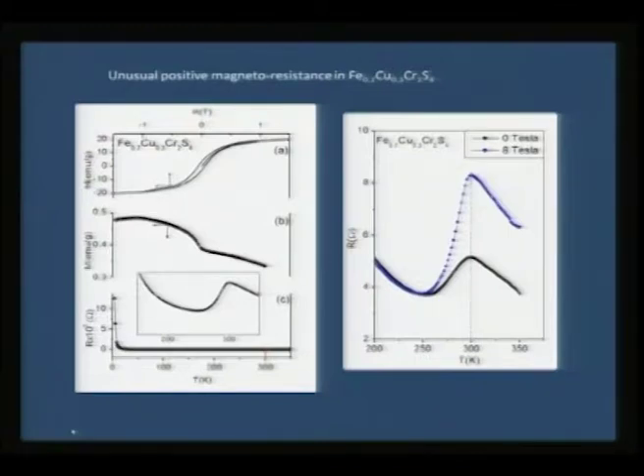But what is fascinating is if you take the 30-70 composition of iron copper, then you see the transition to come somewhere above room temperature. Actually, if you do the resistance versus temperature plot, you would see a typical graph like this, but if you blow up this area, you can clearly see that there is a metal to insulator transition that is happening, which is going with the magnetic property.